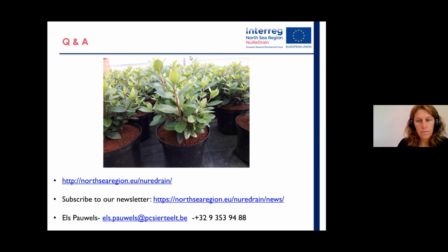The problem here is the availability of the P. You will see in my presentation, you need higher pHs to desorb all the P or a great amount of the P. That's the whole problem. Growing plants, like I said in the beginning, can range from pH 4 maybe till pH 9.